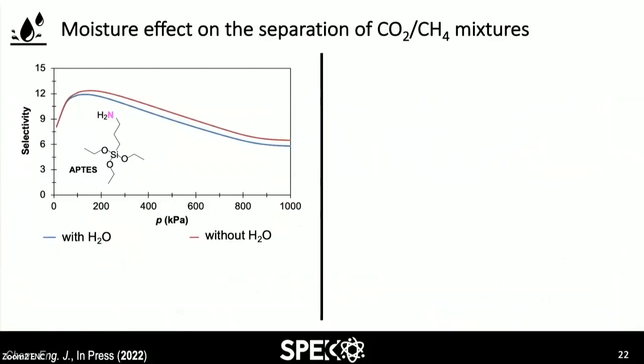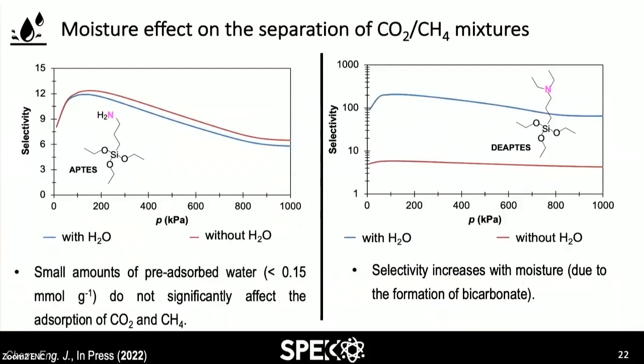And so now, just to finish off my presentation, I've shown you what we did with pure CO2, what we did with CO2 and water, and now we have done a three-component mixture. So we have observed what happens to a mixture of CO2 and methane when you have water. What happens to the selectivity of the material?